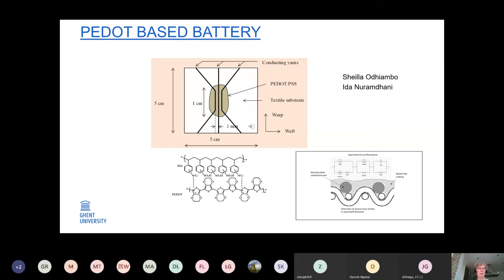We used PEDOT:PSS as an active material, which is a conductive material. You can see the composition here in the slide, and we used it as a coating. So you can see the upper view as well as a cross section, where you can see the conductive yarns that act as an electrode, and the coating itself on the fabric.